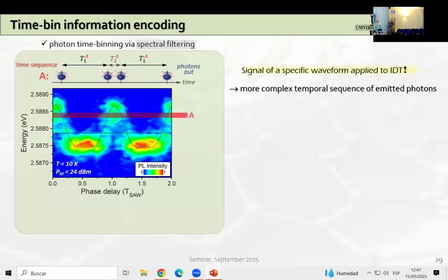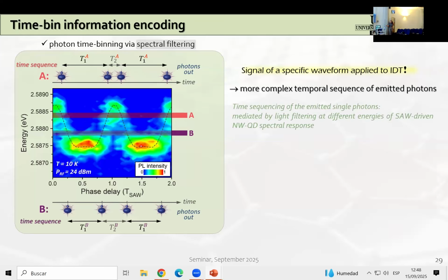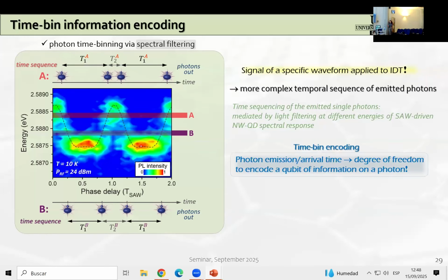So now we see that there is a specific frequency of the photon emission time. They are not equidistantly separated in time anymore. Now, for example, we can select the photons at this energy, in which case we obtain a different time sequence, of course. These time sequences of the emitted single photons are basically mediated by filtering the light at different energies of this acoustically induced fine spectral tuning. This is quite useful for obtaining time bin encoding, which basically, by playing with this waveform, we can obtain all possible options for time bin encoding, meaning long-long, long-short, short-short, and short-long.